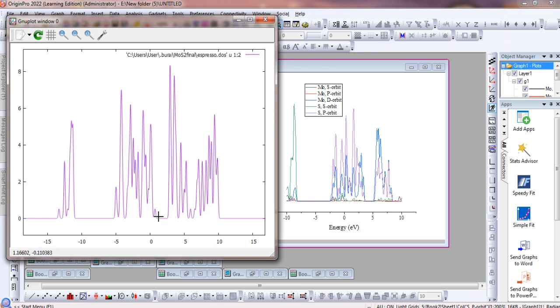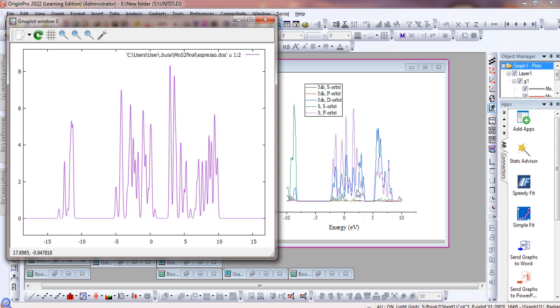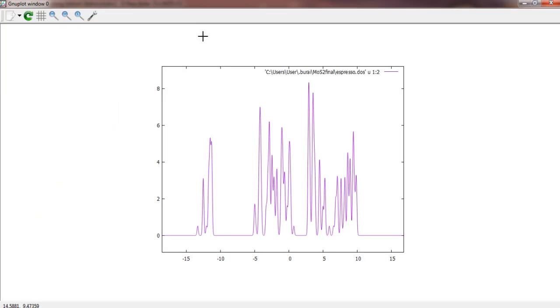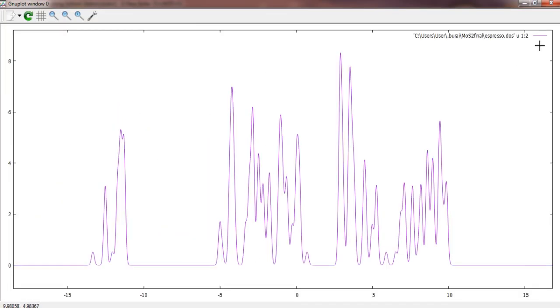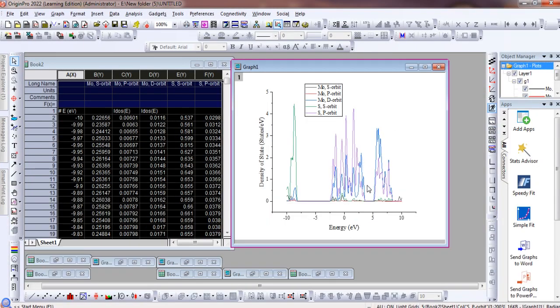In around this point this is our band gap. This is my valence band and in this side this is my conduction band. In between this there is a band gap. Here we can see this blue color line is dominating in the conduction band as well as in the valence band. This is the d orbital, so the d orbital is dominating. This orbital is providing us band gap. The difference of this energy level this will be our band gap energy. After calculating this we are getting the band gap energy of around 1.5 electron volt for this MoS2 material.